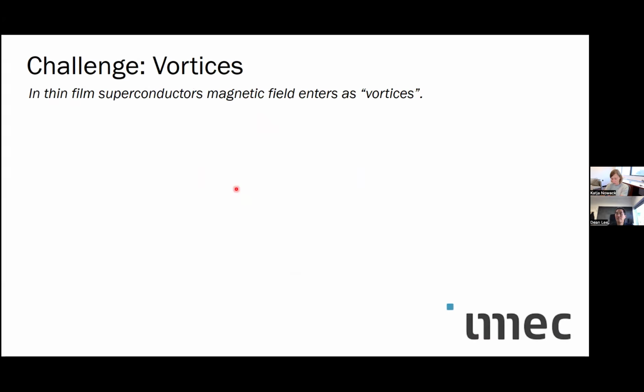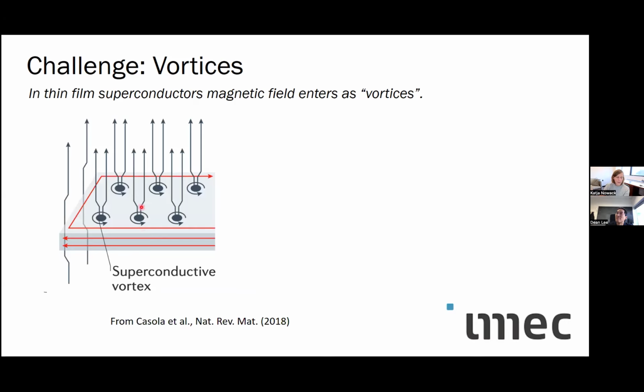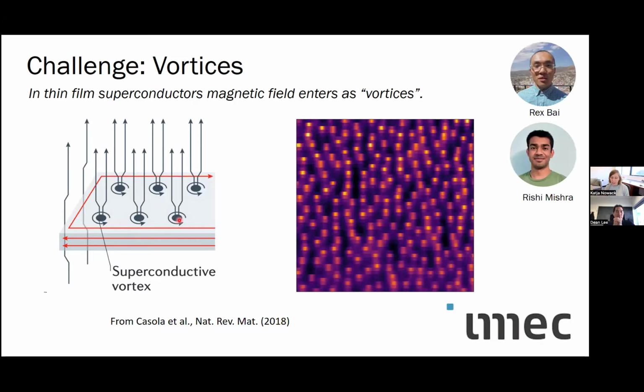Actually, if you apply some field, the magnetic field can enter in the form of vortices. So these are like little pinholes almost, that form in your superconductor, not a physical hole in the material, but a hole in the superconductivity where the magnetic field all of a sudden rushes through. And so those are superconducting vortices. The magnetic field comes through in this hole in the superconductor, and around this hole there are really big swirling currents flowing. And we can image these things.